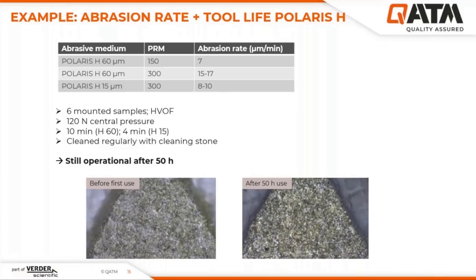So assuming a disc can operate for 50 hours, which is 3,000 minutes, and if you assume that a grinding paper is used for, let's say, 2 minutes, we would need 1,500 papers for the 50 hours. So in this case, the Polaris H disc with 60 micron diamond grains could replace more than 1,500 silicon carbide grinding papers. With this method, the results were very satisfactory and the layers didn't break out. Therefore, it is possible to develop alternative methods to conventional grinding paper preparations.